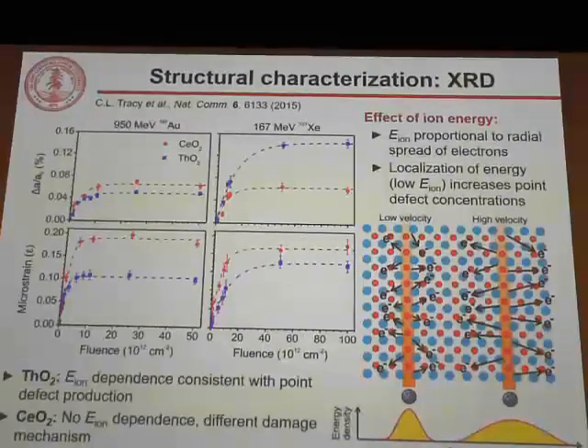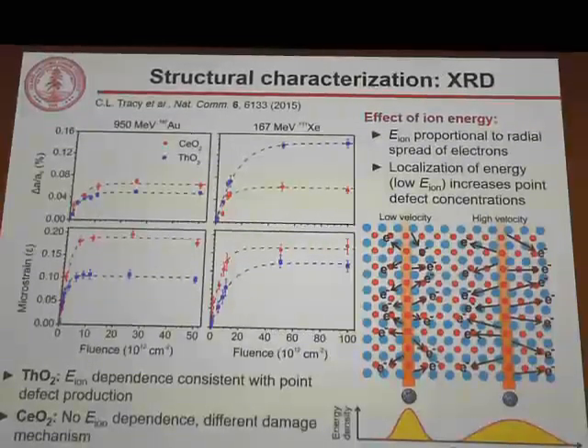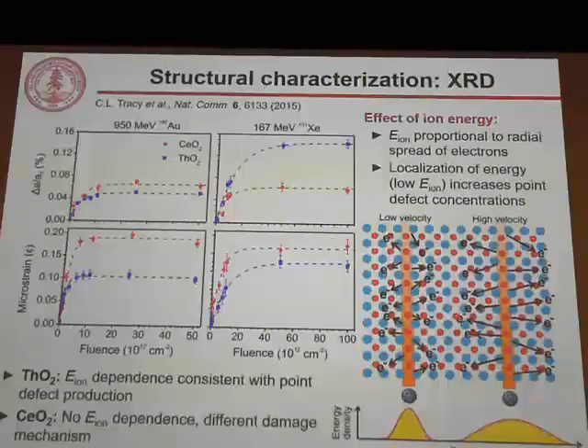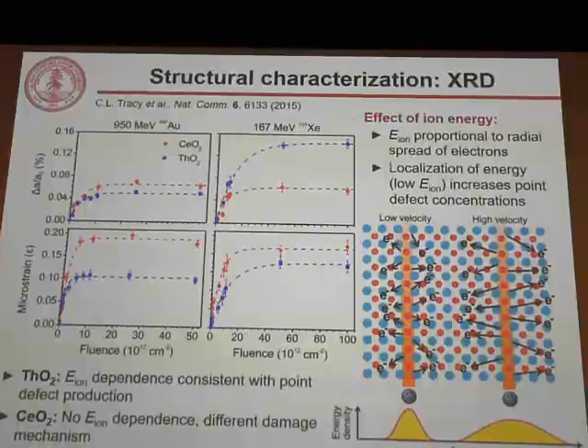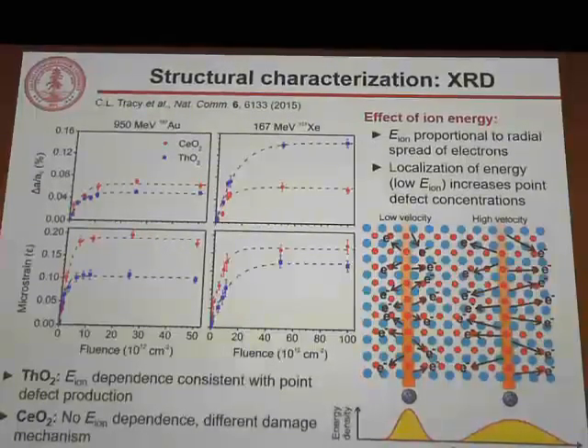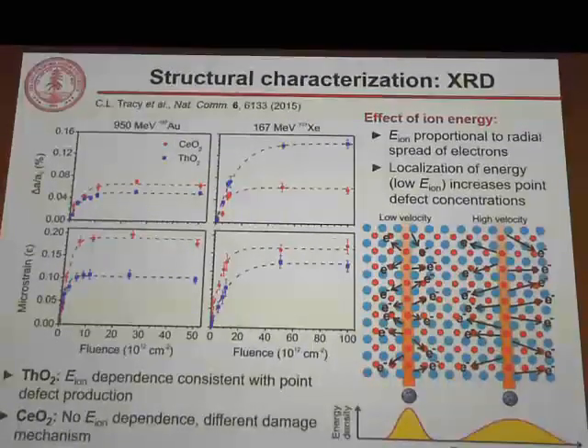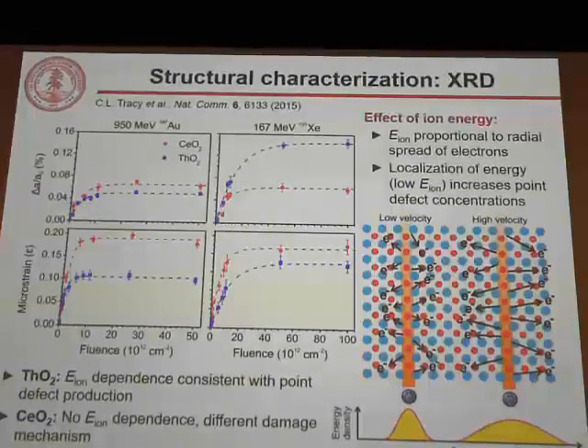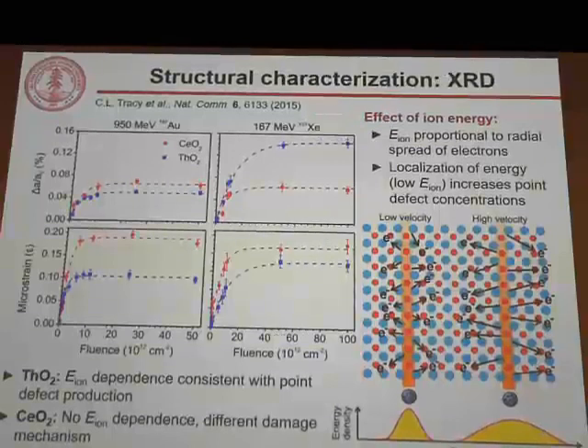What we can conclude is that in thorium dioxide, due to the ion energy dependence we observe, we can attribute the damage observed to typical point defect production mechanisms of damage accumulation. In cerium dioxide, we do not see this expected ion energy dependence, so there's likely a different damage mechanism.